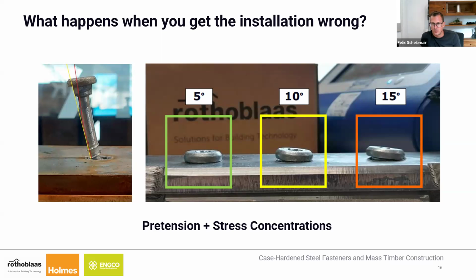If you look on the left-hand side, the other outcome there is that you damage the coating of the screw. So that's particularly important for zinc-coated screws, because at that damage point, you then get extremely accelerated corrosion, which will lead to failure of that fastener at a much, much lower capacity than is intended by, I guess, us as screw manufacturers and the designer, because the hydrogen embrittlement really does come in quite quickly then and can happen at lower moisture contents than expected.